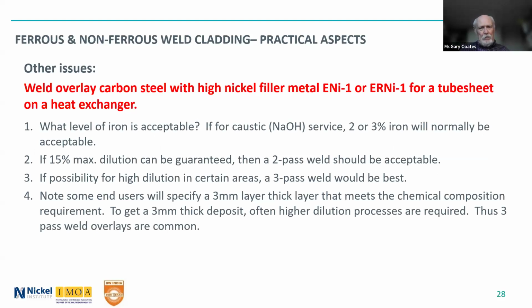Because if the end customer then does an analysis of the top layer there, and he finds that it's actually 5% iron, he may reject it, and you may have to start all over again. Some end users will specify a 3 millimeter thick layer of the weld overlay that meets that composition requirement. And so sometimes you need to do a higher dilution process to get that thickness, as we saw from the earlier slides. So 3-pass weld overlays are actually fairly common when it's a very severe service.